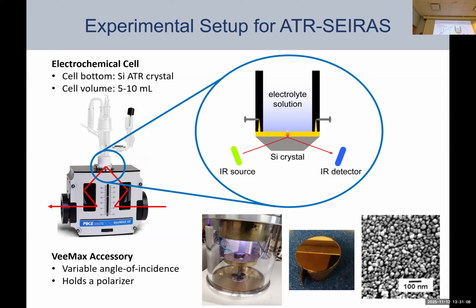So here you can see a picture inside our argon sputter coater, and this is the silicon crystal after sputter coating, and here's an SEM of the surface. Now this technique used to work really well for me, and it doesn't work well for us anymore. So this is what I meant by there's some challenges here in film preparation, and again, I'm happy to talk more in detail if people have questions.